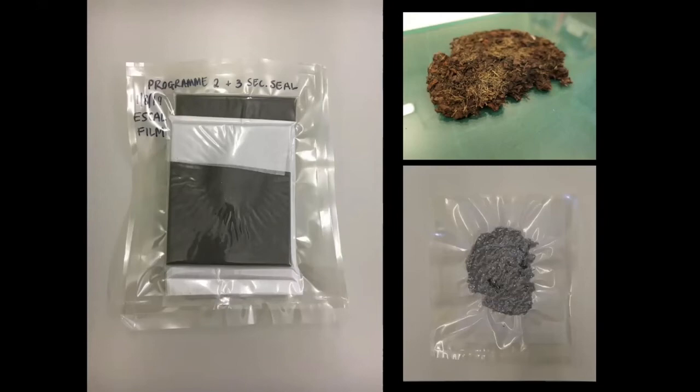To ensure the optimal stability of PMA5 within a vacuum sealed enclosure, we used Escal film recommended by John Gillis. Escal film is specifically designed for the long-term storage of museum objects within a vacuum environment and was thoroughly investigated by John during his PhD research on the conservation of the Faddan More. The inner layer of Escal is polypropylene, whilst the outer barrier layer is a vacuum-deposited ceramic on a PVA substrate. The film has known oxygen permeability and water vapor transmission, keeping the enclosure content stable for at least 50 years.